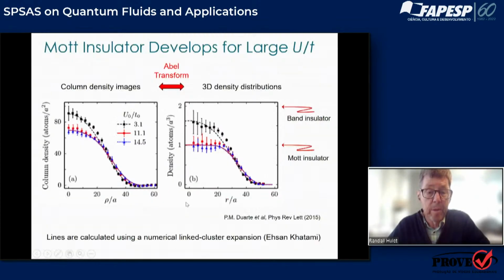So in doing that, we were able to realize a Mott insulator, a very nice depiction of the Mott insulator. The different colors, let's look on the right-hand side. These are symbols or data. The black symbols correspond to U of 3, the red ones to U of 11, and the blue ones to an even stronger on-site interaction of 14. And you can see by the time you get to 11 that there's a central plateau where the density is very, very constant at 1 per site. So this is a manifestation of the fact that this has become a Mott insulator, where there's now a Mott gap. And in fact, this region where the density is fixed at 1 is very incompressible. The atoms don't like to move.